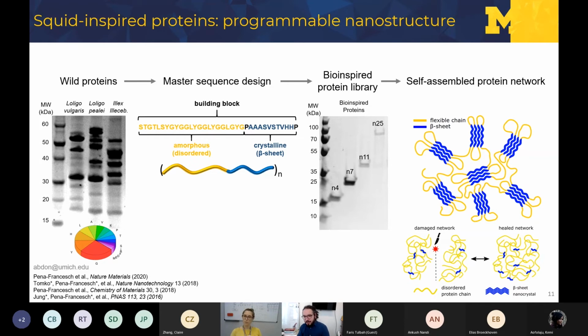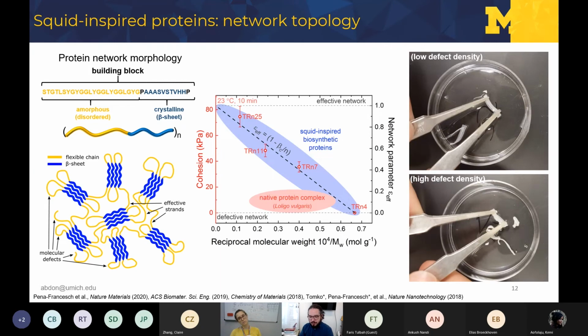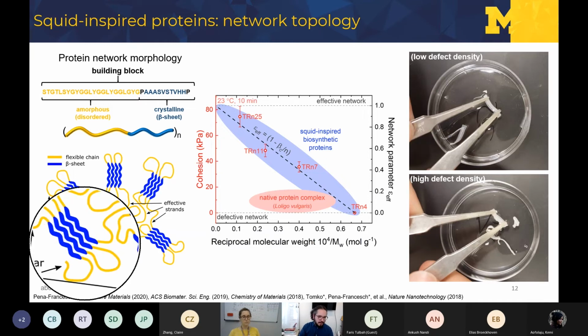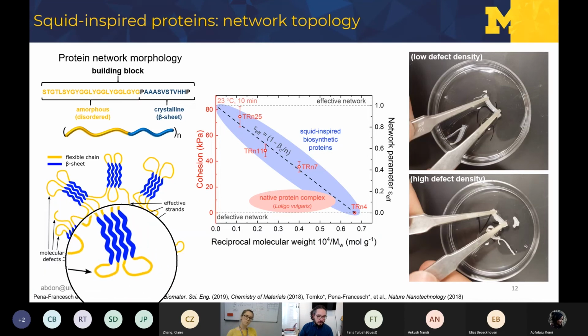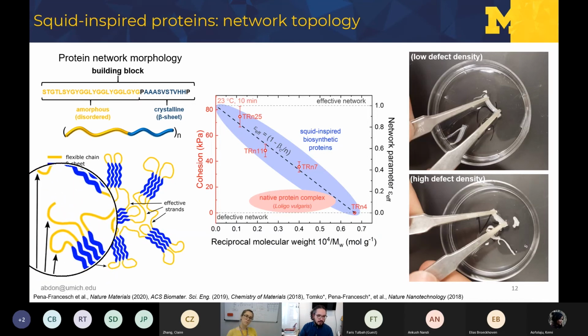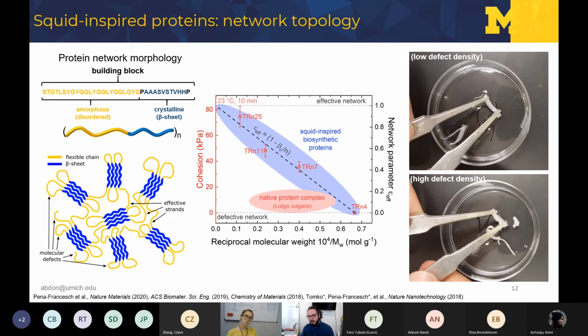But as you can imagine, this brought a lot of problems. One of the big ones was that when you have self-assembled nanostructures, you end up with a lot of molecular defects, right? The molecular defects being things like dangling ends or loops in your structure, chains that are not really contributing to the material's properties, right? Think, for example, of mechanical properties: when you stretch your network, these will not bear any load, any stress, right? So they're detrimental to your structures and to your properties.